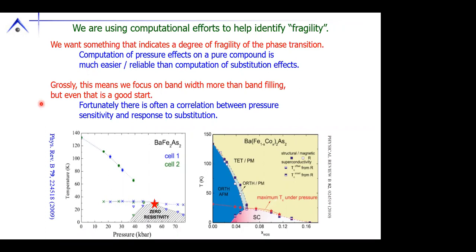But that's okay, because in many of these superconducting systems, we see that the effects of doping, here's cobalt doped barium iron 2 arsenic 2, we suppress antiferromagnetism, orthorhombicity, get a dome of superconductivity. The effects of doping are very similar to the effects of pressure. Here's pure barium iron 2 arsenic 2, we can apply pressure, we suppress the antiferromagnetic orthorhombic, and we get a dome of superconductivity. So maybe we can use computational studies on pure materials under pressure to give us some hint of what might be promising.